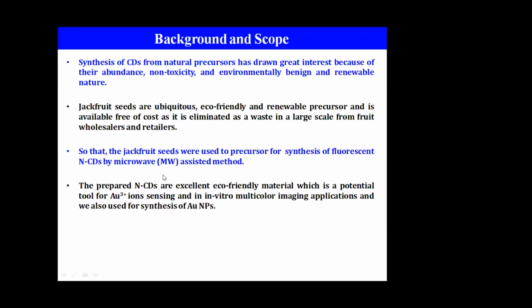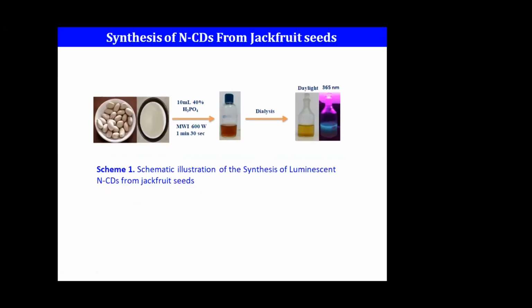The CD we obtained was an eco-friendly material and a potential tool to sense gold ions—sensing gold ions worked with this material. We synthesize it using a microwave with a power of 600 watts, for a shorter time than what we used for algae—almost 1 to 2 minutes. Once you have the material, you dialyze it, purify it, and use it.